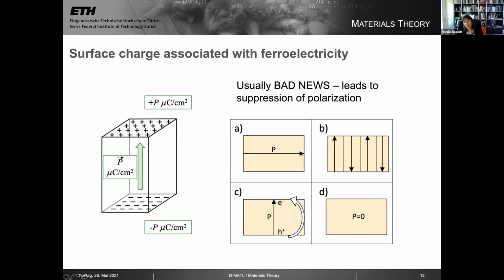So for example, the polarization might go in plane, right? Because if I have a film and my polarization is in plane, then I don't have any surface charge on the surface. The polarization might split up into domains, because then I have only a little bit of positive charge here and then immediately some negative charge. So averaged over this whole surface, I don't have so much net charge. The system might spontaneously generate electron hole pairs to compensate the charge. So it might make excitations of electron hole pairs across the gap, so the electrons can come and sit on the positive surface and screen and kind of neutralize the surface charge. The holes can go to the bottom surface.